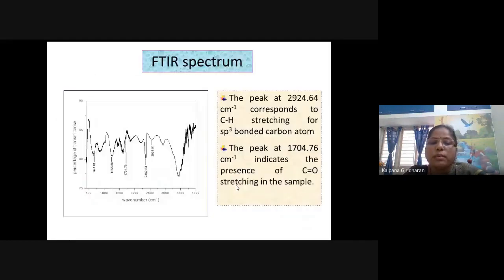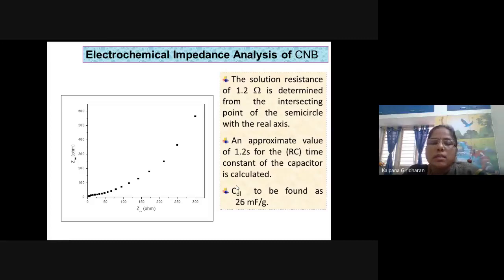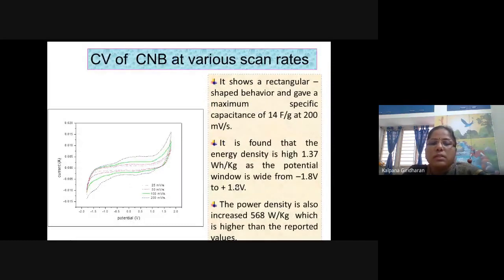I will show you that. This is the FTIR spectrum, not much to tell. And this is a typical Nyquist plot - you can see the solution resistance is very minimum, around 1.2 ohms, and the double layer capacitance is around 26 millifarad per gram.